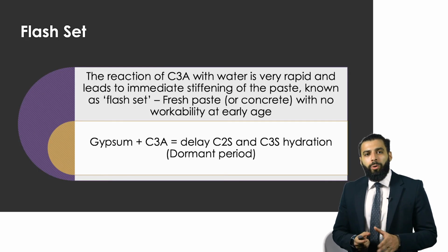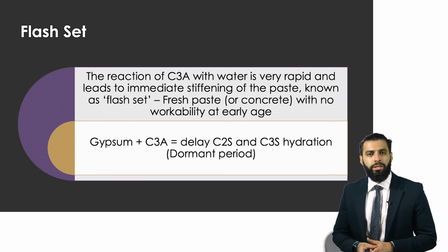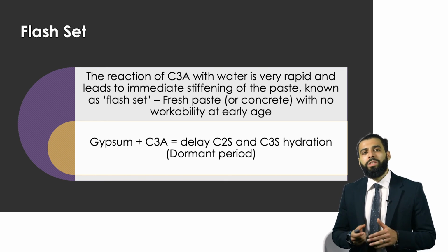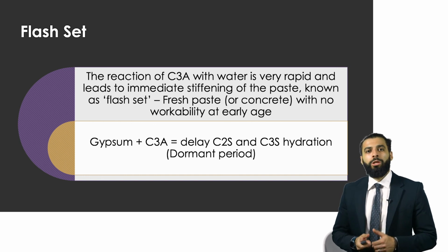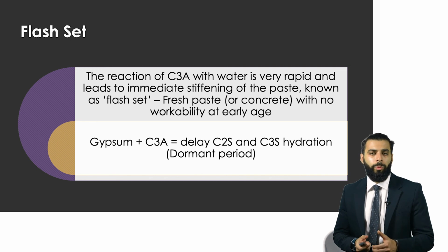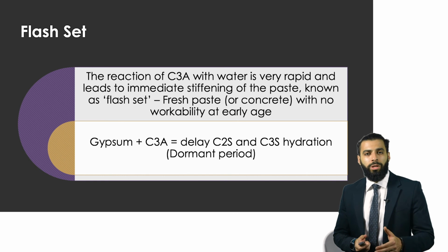Now, this is a very important point to discuss, and that's flash set. Now, flash set, the importance of studying C3A, as you've seen, there's no major contributions to strength. However, what C3A does is that it controls the setting of the concrete. So if you control its hydration rate, you control the setting of the concrete, and this is very important, for instance, when you're transporting your concrete to construction sites that are located very far away.